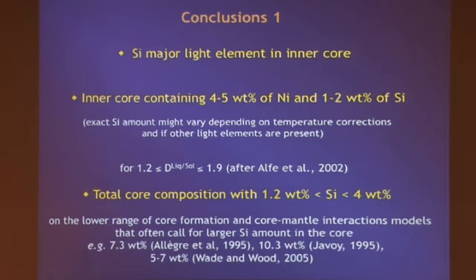of temperature correction. There is clearly a compensation effect between temperature and silicon. The higher the temperature, the more silicon you can put. But assuming a reasonable anharmonic correction taken from an ab initio calculation, we end up with this result. It can as well be partially affected if other light elements are present.